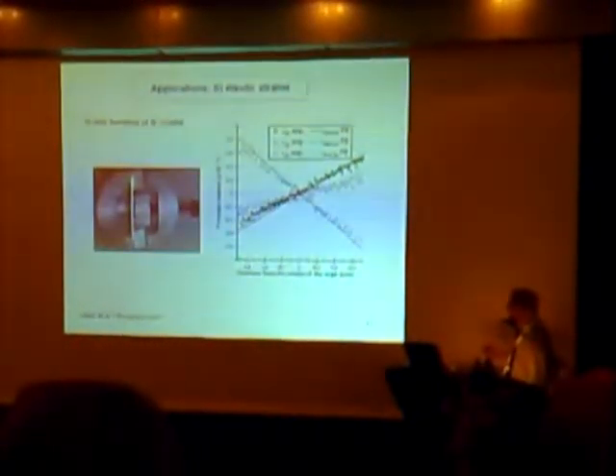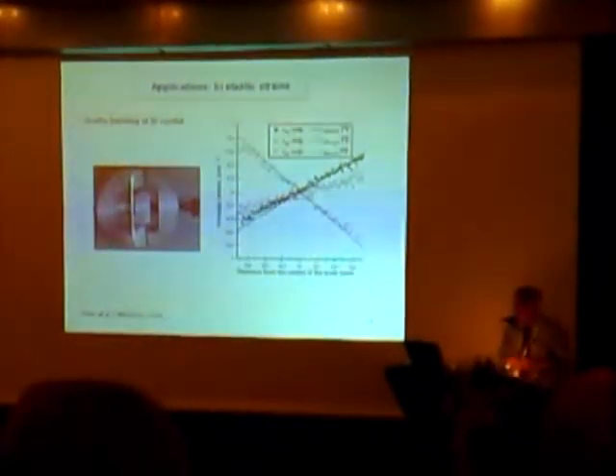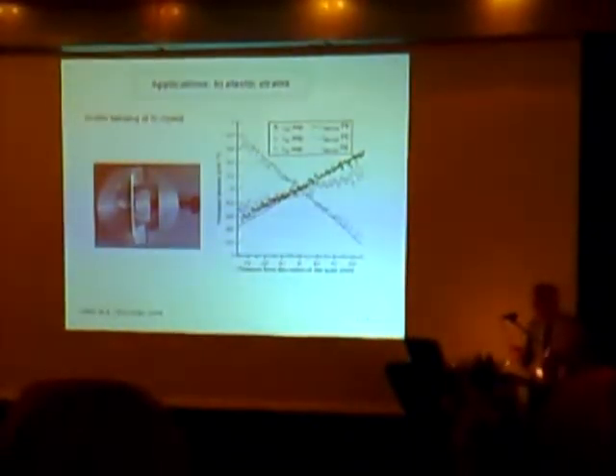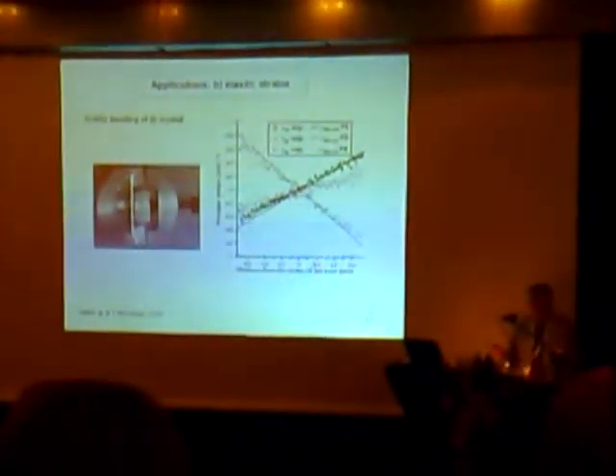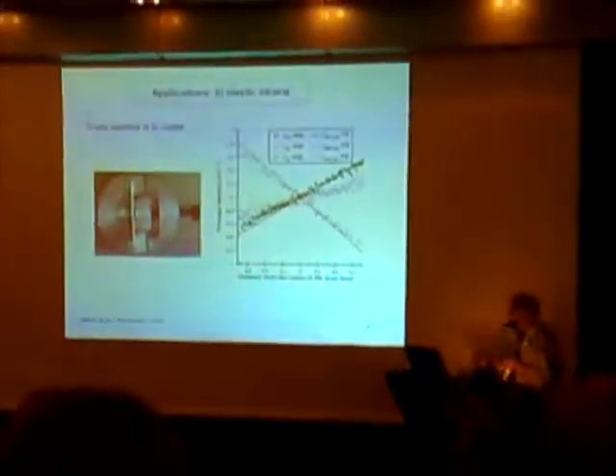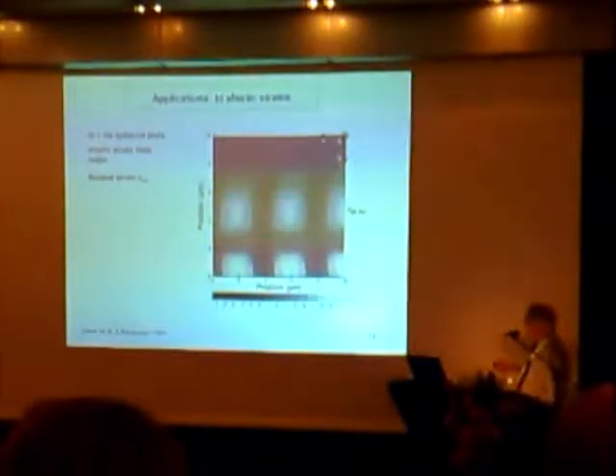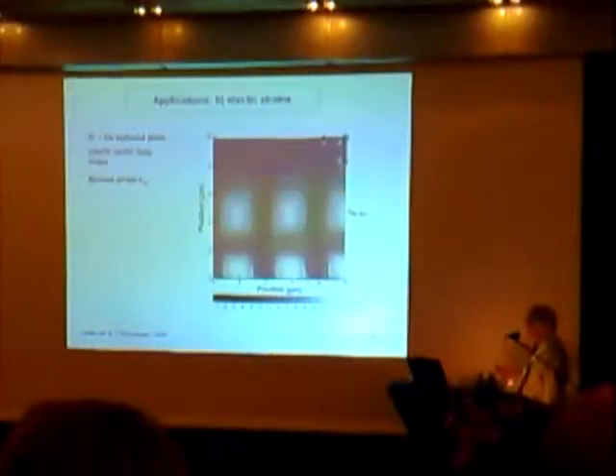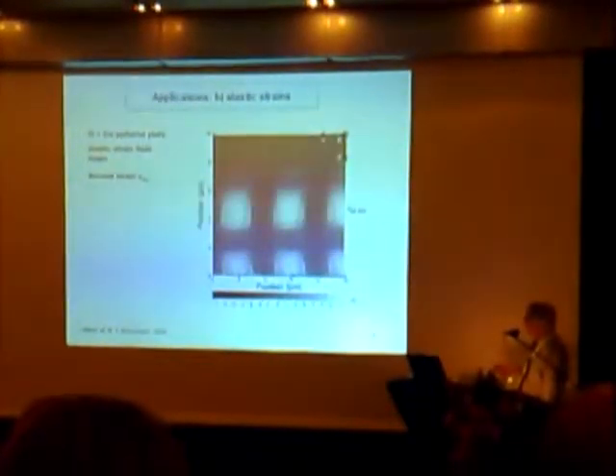So within about this area, this is about 10 to the minus 4, or 2 times 10 to the minus 4. So it is true. You can measure elastic strains to this type of accuracy using high angular resolution EBSD. Now, if you can do this, you can go back to what Truce did and looked at silicon germanium epitaxial plots. And this is a map of elastic strains. Here is just showing the normal strain component.